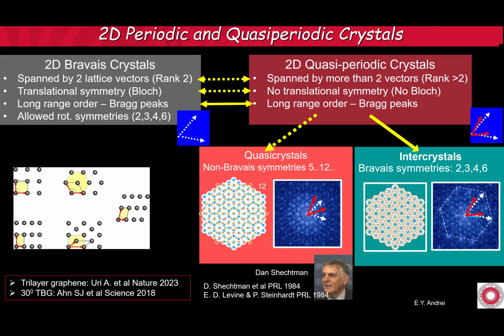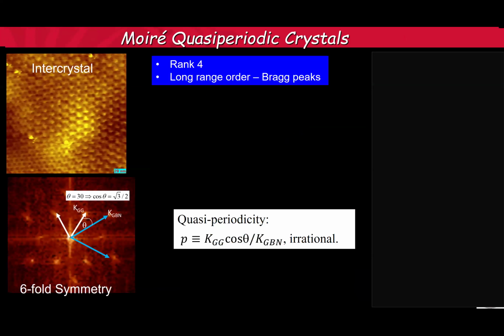Okay, so in graphene, people have seen a quasicrystal. You have to rotate by 30 degrees, and then you get a quasicrystal, but it's only one point. And the symmetry of that is 5 or 10? It was 10. Okay, so here is an example. Here's an intercrystal. We have two lattice vectors, and the angle between them is 30 degrees. When the projection of one of the lattice vectors on the other is irrational, that's when you can say you have quasiperiodicity. There are all sorts of caveats on that, of course, because we have a finite sample.